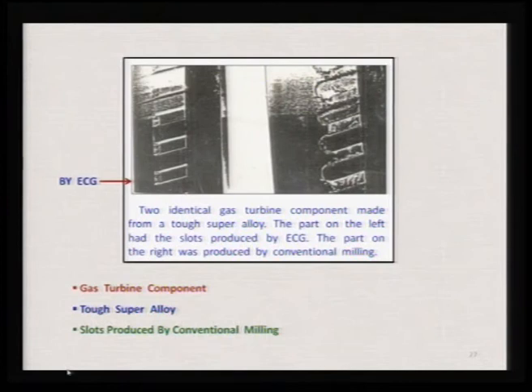You can see here two identical gas turbine components made from a tough superalloy. The part on the left hand had the slots produced by electrochemical grinding. On this side you can see clearly. The part on the right was produced by conventional milling, and you can see a lot of burrs and inconsistency in the size of the burrs, while on the left side there are no burrs. So, it can be used for gas turbine components, for grinding of tough superalloys, for producing slots.